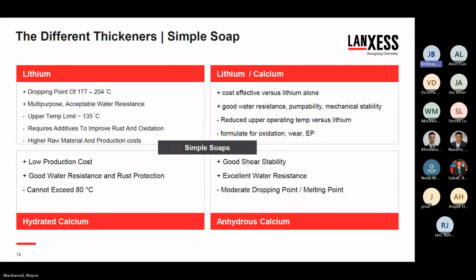They're actually excellent greases. Dropping points are typically around 200 degrees C or a little bit above, and with different additives, you can bump that up a bit. They're a multi-purpose grease with good water resistance. Their upper temperature limit is about 135 C. But for the majority of applications, lithium works pretty well. Of course, you have to additize for just about everything in terms of performance, but a lot of work's been done, and there's certainly a host of chemistries out there to make these into decent greases.